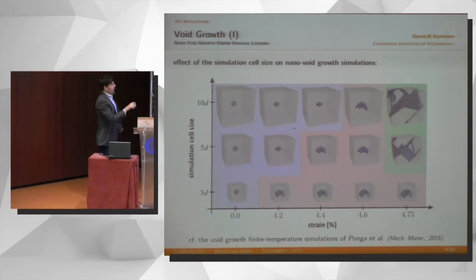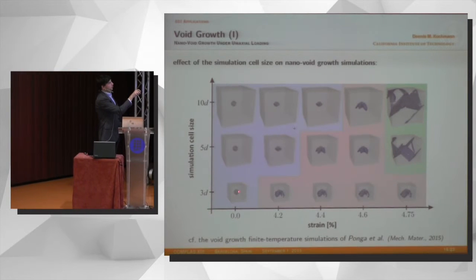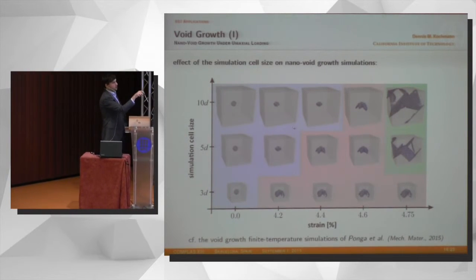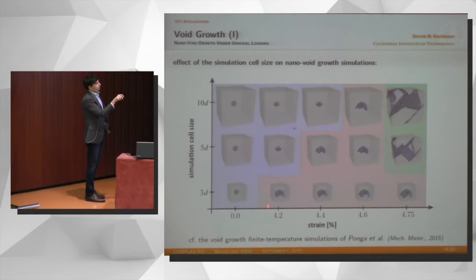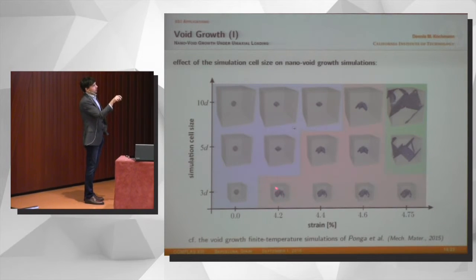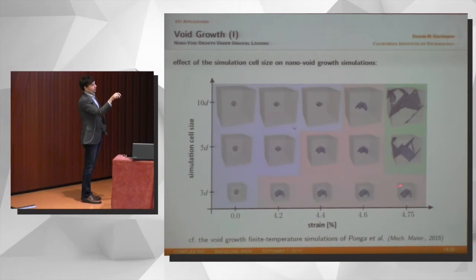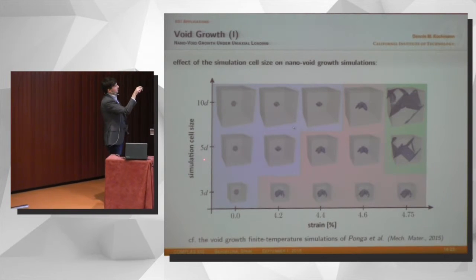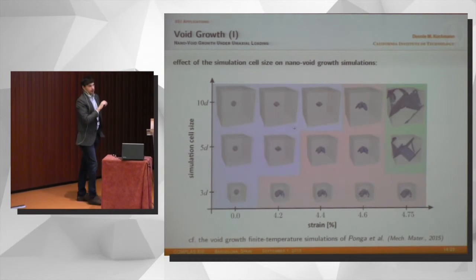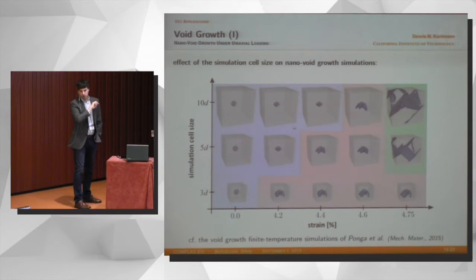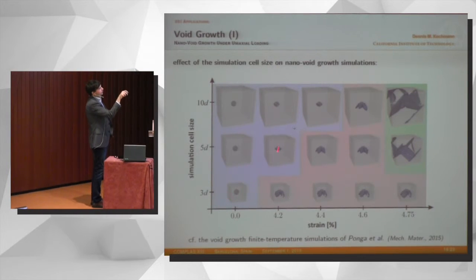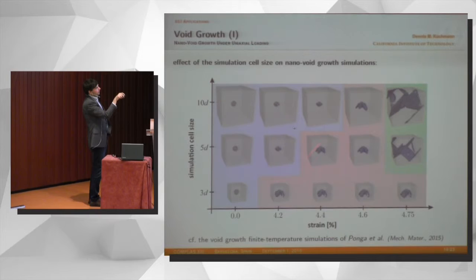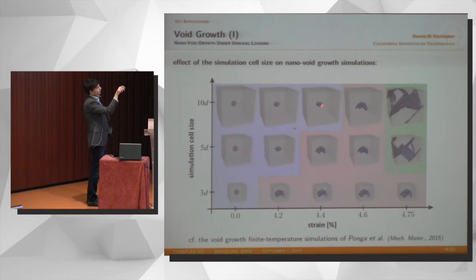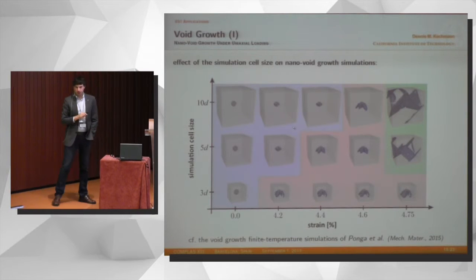That's exactly what you see down here. This is a nanovoid in a very small cell, and I'm increasing the strain at which I'm loading the unit cell. At a strain of 4.2%, you see dislocation loops emanating, and they grow, and they keep growing, and they do funny things. This is the same simulation with a slightly bigger unit cell, and this is the same simulation with an even bigger unit cell. And you can see that the first nucleation of dislocation loops coming out of the void is significantly delayed by the fact that we're using a bigger unit cell.